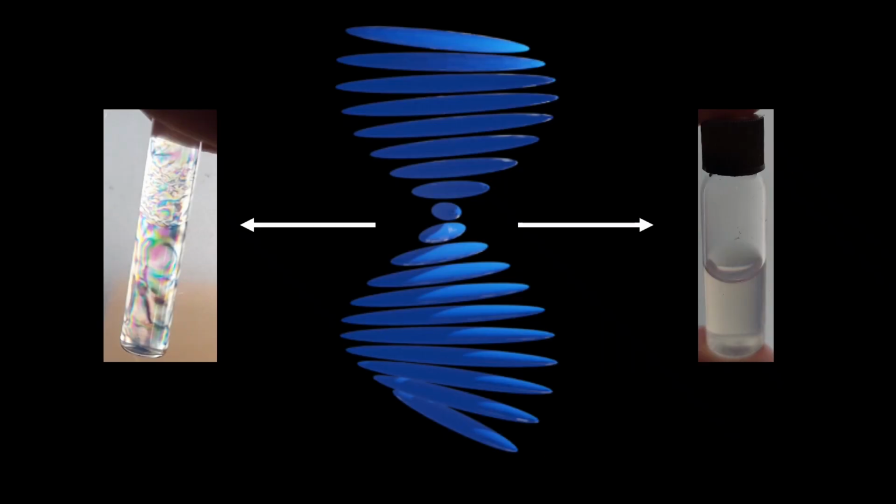So if we want to get a specific color or not, and a specific viscosity, we need to consider at least several factors. Those systems which show colorful behavior act like liquid crystals. And color is a result of self-assembling particles. In turn, the lack of color is due to strong attractive forces which lead to color fading, the material will become opaque, and at the same time viscosity will increase. And both these features can find their usage in potential applications.